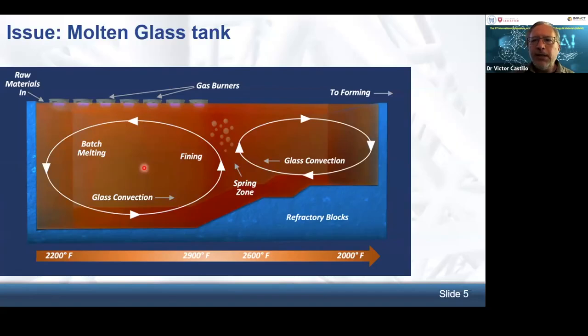One thing that you get with some of the problems is with the outgassing, you can actually get the bubbles coming to the top and the foam rising to the top and moving towards the forming. And so what they're trying to do is get the foam moving to the left so that it subducts and is dissolved into the molten glass. Another problem is if the convection is too vigorous, it will actually cause the raw materials to go out toward the forming, and then you have uncooked raw material.